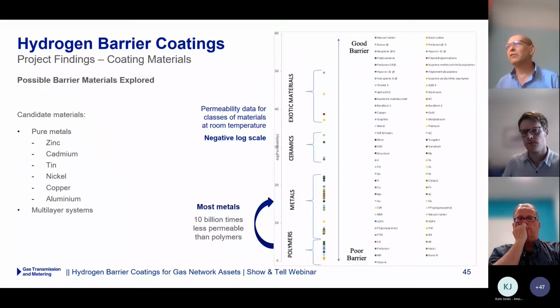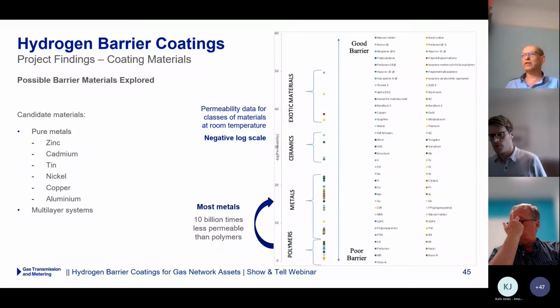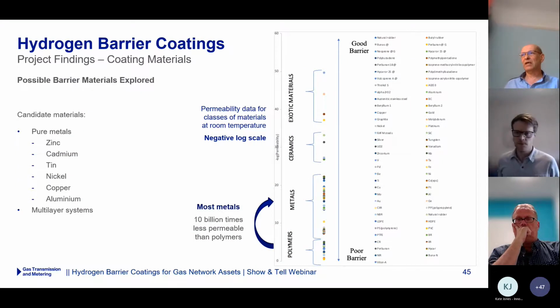Thanks, Rob. In the discovery phase, we investigated a wide range of potential hydrogen barrier coating materials that you can see in this table here. The most useful parameter for comparing materials is their permeability characteristic for hydrogen. The data we have on the slide for room temperature shows that the most effective hydrogen permeation materials actually come from things that are not very practical to apply at scale, like ceramics and even more exotic materials like single crystal silicon.